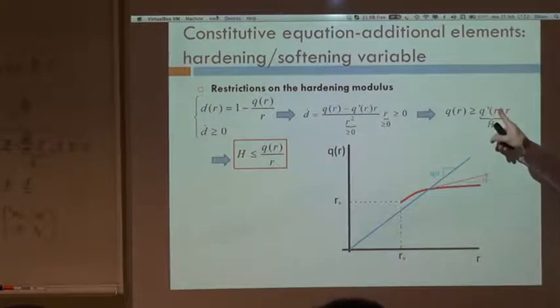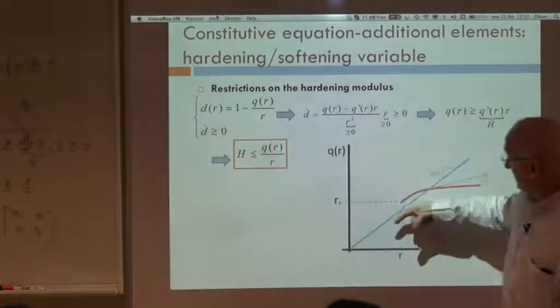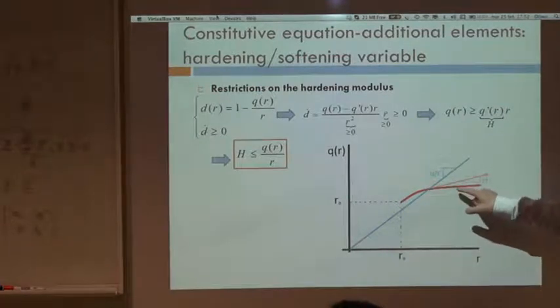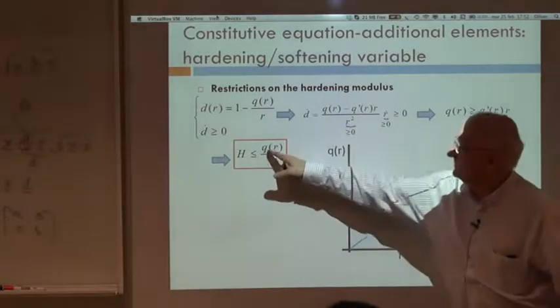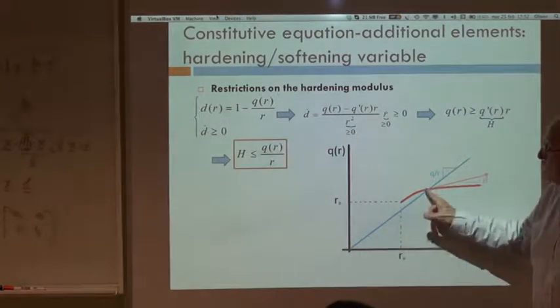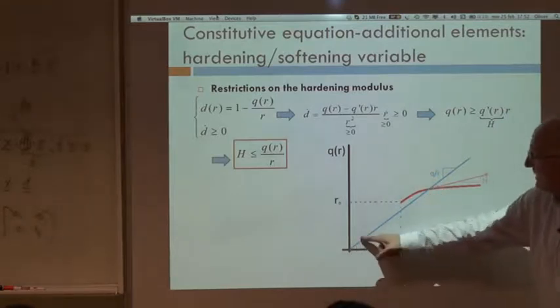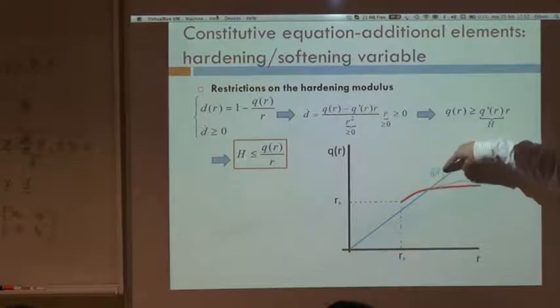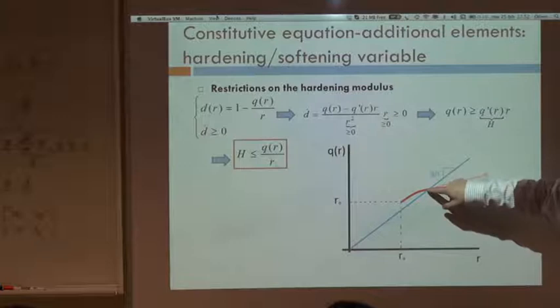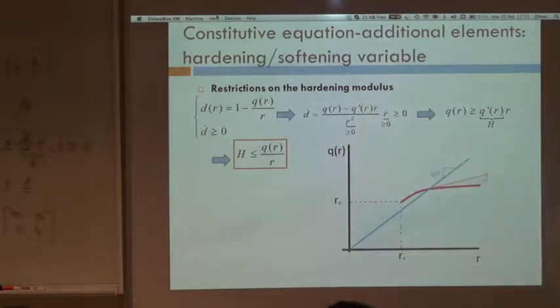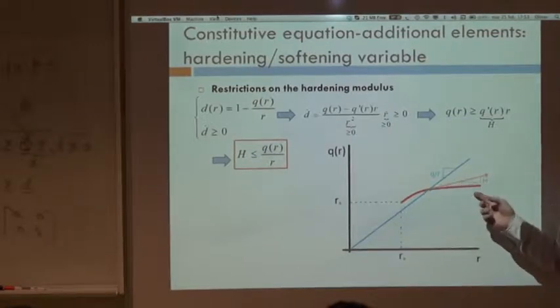In order for D-dot ≥ 0 to be fulfilled, the numerator has to be greater than zero, which means H — the slope of the hardening law — has to be at every point smaller than Q over R. Q over R is the slope of the secant line. This is not very restrictive, but we have to be consistent. If you invent an evolution that is not compatible with that, we can have unusual and unexpected values — and that is our fault in inserting the properties of this constitutive model.